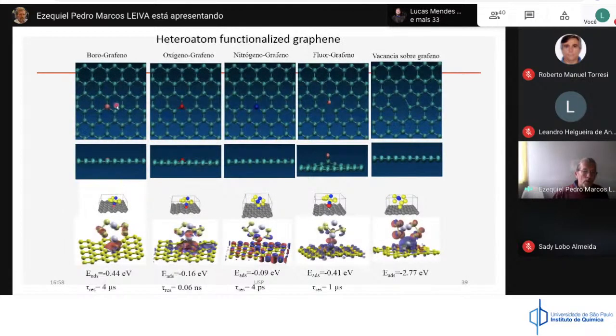Well, we considered different surfaces, substituted with boron, oxygen, nitrogen, fluorine, and the vacancy. We studied different systems and calculated the energies, and from this energy you can make an estimation of the time. Here you have some estimations of the time depending on the energy. For instance, with an adsorption energy of 0.44, you can get a residence time or retention time of 4 microseconds, which is very small.